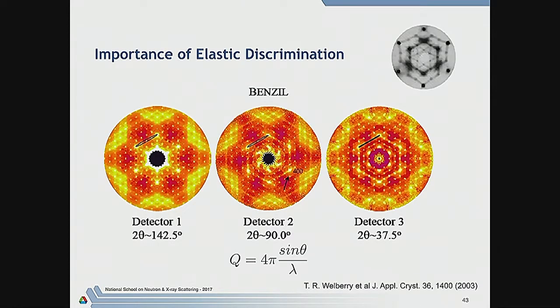So why is it a particularly exciting time at the SNS? If you go back to that benzil case, the molecular solid, you remember it had this beautiful diffuse scattering. When it was measured on SXD, they noticed something rather interesting in the data. This is sort of almost like Bragg's law, but what we can see is that for any particular Q, you can produce that same Q either by going to low angle or by going to higher wavelength. And so you can actually produce the same plane of scattering using different detectors at different angles and different wavelength ranges, okay? And this is apparently the same Q range, and yet it looks entirely different.